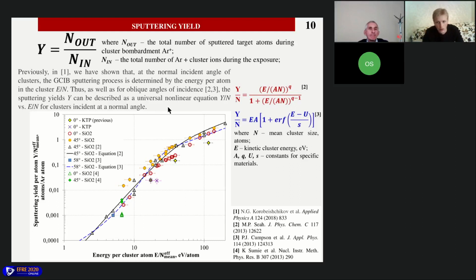Recently, it was shown that sputtering yields can be described as a universal non-linear dependence of the sputtering yield per atom on the energy per atom in the cluster. Non-linear dependence is typical for various materials, including potassium titanyl phosphate. The sputtering yields are plotted in this figure, and here you see different sputtering yields of different materials, and the non-linear dependence for all of them.